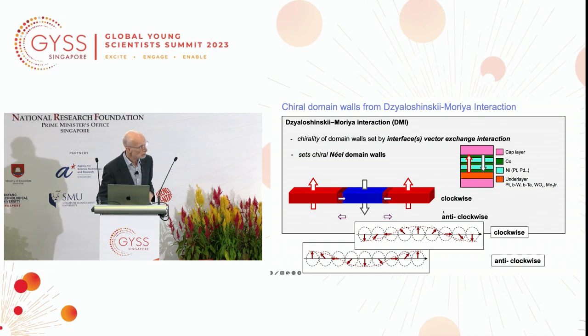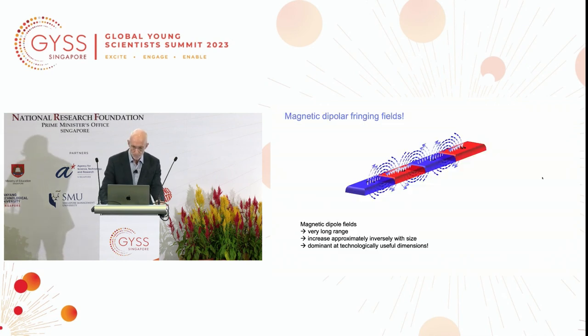We grow our regular materials. The racetrack is typically made from, let's say, cobalt, nickel, cobalt. These layers are 1 or 2 to 3 angstroms thick. And underneath, we have this orange layer, which could be platinum. Platinum not only gives the spin Hall effect and spin currents, at the interface, it gives rise to a very interesting type of proximity exchange, which is called a Dzyaloshinskii-Moriya vector exchange, which gives rise to these chiral structures. Very important. And another point we have to take advantage of or take control of are dipole fields. So you all know that a magnet generates fields.